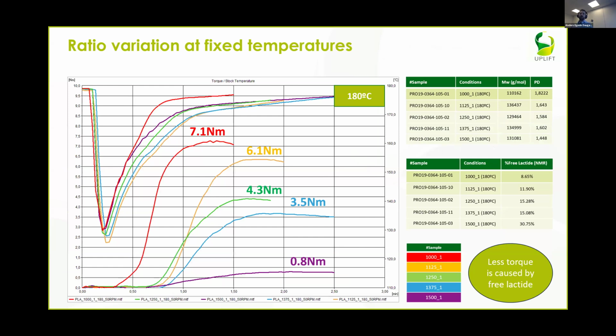And you can see the ratio of catalyst to lactide in the system directly reflects on how much polymer is actually achieved. But the take-home message from this is that it is a highly active catalyst that is able to produce PLA under continuous processes with relatively little excess lactide being present in the system. So it's a way to scale the process to make it economically a bit more feasible. It makes a much faster polymerization than is otherwise possible through ring opening polymerization, and therefore also lends itself to supporting this bio-based transition.